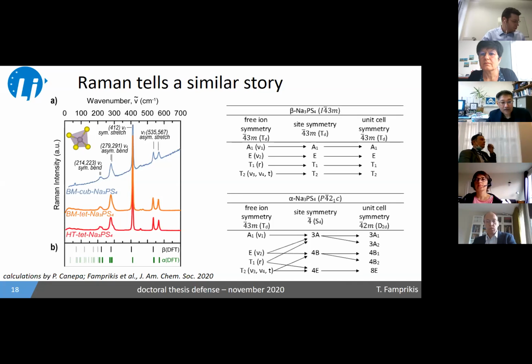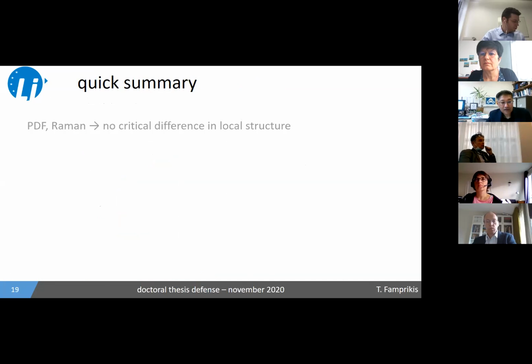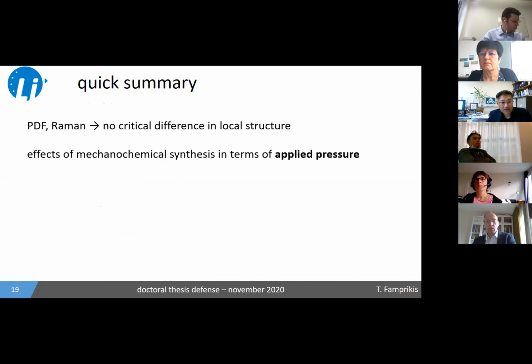So that's why you get the splitting of these 2 peaks. Here, 3 here, 4 here. So basically, PDF and Raman both tell us that there's no critical difference in local structure between the mechanochemically synthesized sample and the solid state sample. They're both equally tetragonal. And the effects of mechanochemical synthesis can be somehow understood in terms of applied pressure.